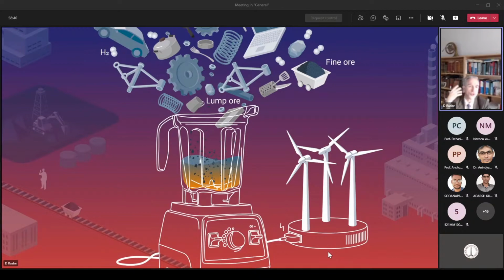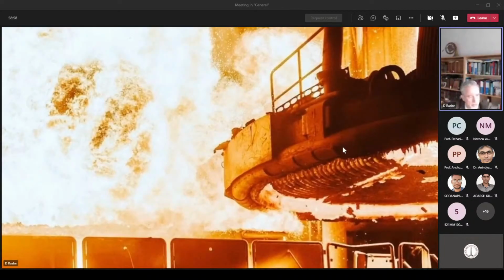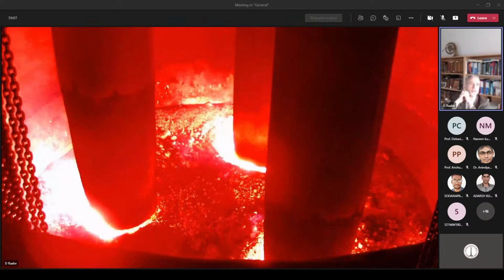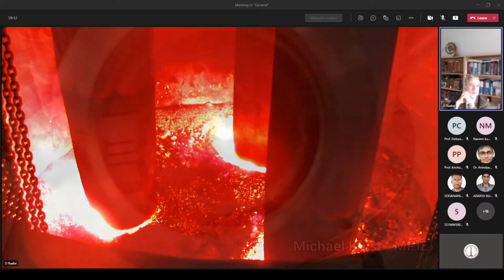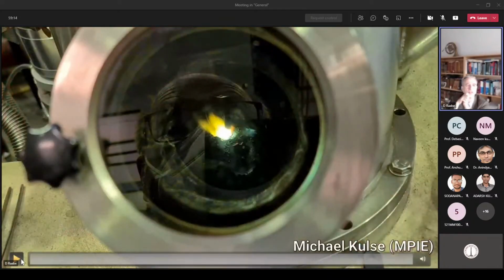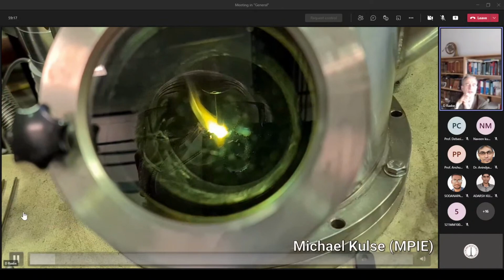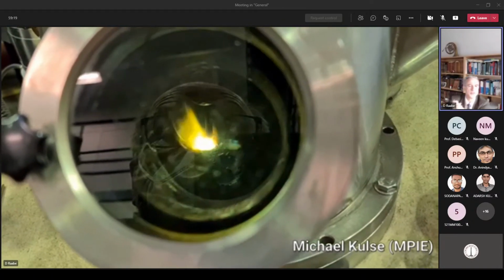And then you charge your ores, your scrap, you can mix everything and melt it. You must not forget the melting point of hematite is only slightly higher than that of the iron. And that means you really can co-melt scrap and hematite, and by that also reduce it. And of course, we all know that these electric arc furnaces are a global industry standard. So that's a growing market, and in all the steel producing countries, this is a total standard technique for scrap melting, particularly for stainless steels. But it can of course be used for any scrap material.